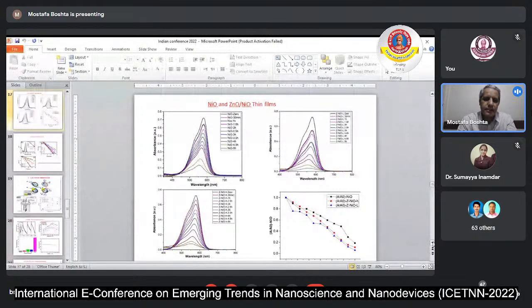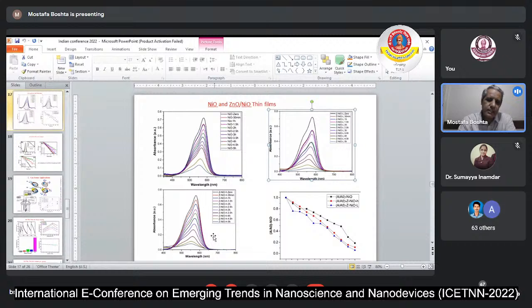Also, nickel oxide, we can try to use nickel oxide as a photocatalytic material for some dyes also, but in this way we can use it as two layers. We deposit nickel oxide, and on the surface of the nickel oxide we add a zinc oxide layer, but the zinc oxide layer here is deposited by CVD, chemical vapor deposition, not by spray pyrolysis. So we can test this material, and as we can see with two different thicknesses of layers of zinc oxide, the lower thickness of the zinc oxide layer on the surface of nickel oxide gives us more decay than the thick zinc oxide layer on the surface of the nickel oxide for the photocatalytic application and for the dye cleaning from the solution, as we can see here from this curve.